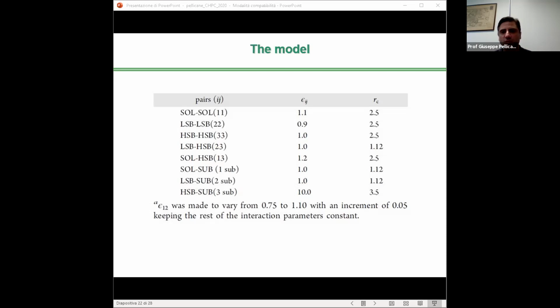So the interaction potential of all beads with the substrate is also modeled by a Lennard-Jones potential. However, the strength of interaction of different blocks with the substrate varies depending on the wetting preference of the substrate. We made use of a strong substrate-HSB interaction energy, as you can see in this table, which is equivalent to a strong hydrogen bonding interaction between the HSB block and the substrate. Solvent-substrate and LSB-substrate pair interactions are considered to be purely repulsive to make the substrate strongly selective to the swelling block only, that is the HSB block.